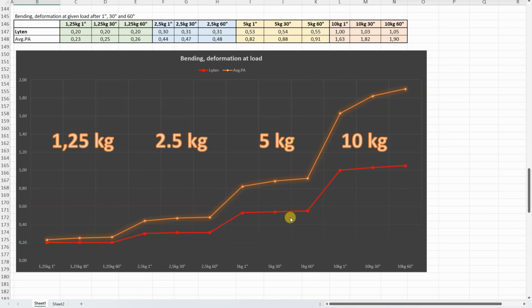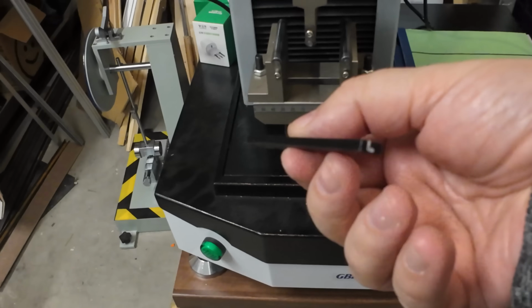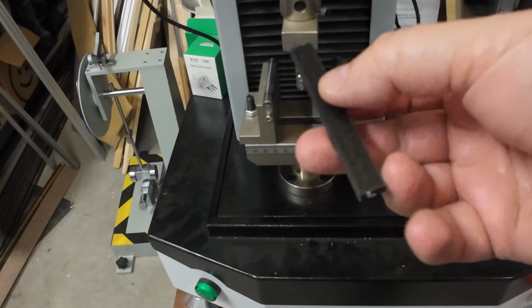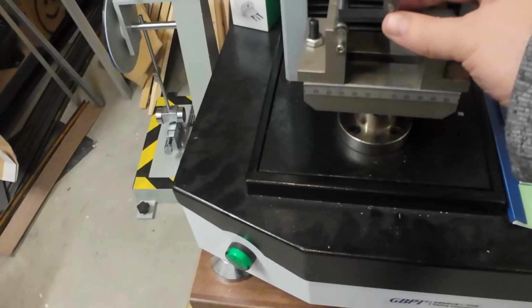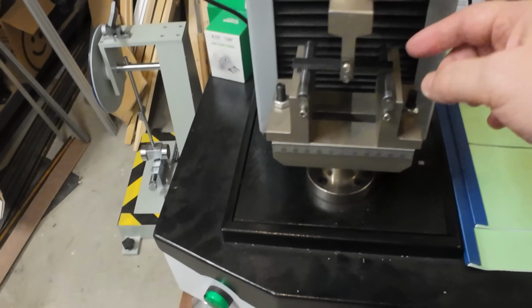Noticeable smaller deformation on the Lyten compared to the average fiber reinforced PA, but what is important is this deformation under 10 kilograms. Yes, even this Lyten has some additional deformation during that 1 minute and it's quite constant, but much smaller compared to the average fiber reinforced PA. And since the permanent deformation is basically 0, I decided to use these test objects for one more testing in